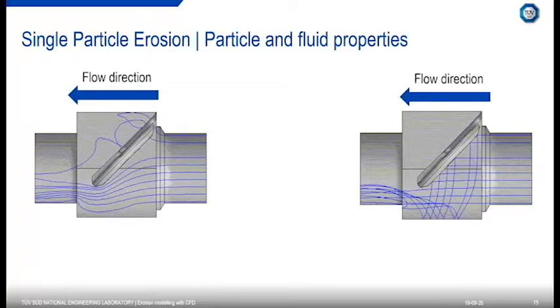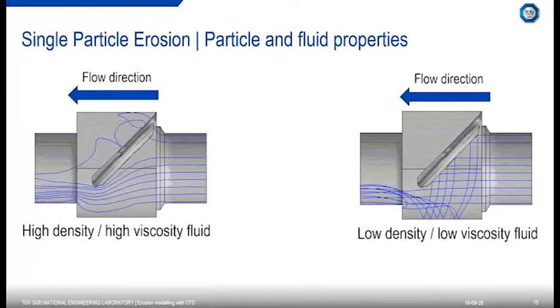So in the left-hand image, the particles flow around the valve body, and in the right-hand image, they impact the body. And this is essentially governed by the inertia of the particle relative to its fluid media. So if we consider a constant-sized particle, traveling either in a high-density, high-viscosity fluid, or a low-density, low-viscosity fluid, so if we have the particle carried by a high density, high viscosity fluid, such as a liquid, this allows the particle to stay within the flow and follow the streamlines of the flow. And that's shown on the left-hand image.